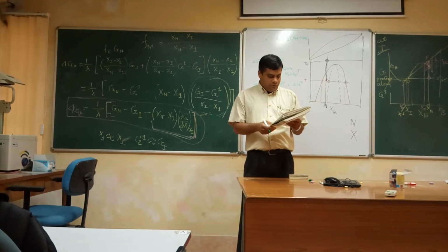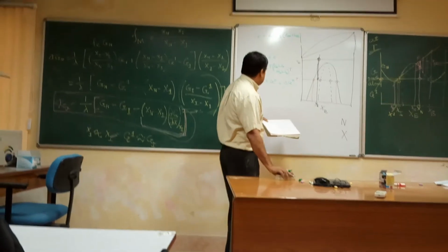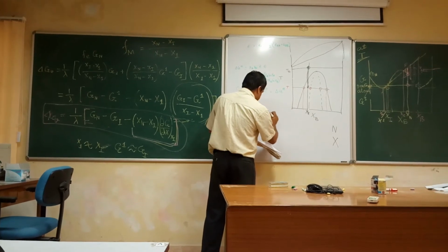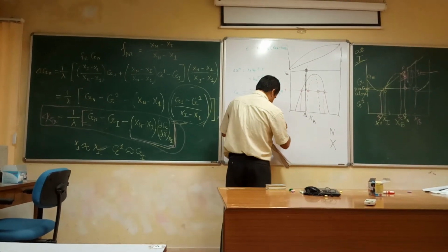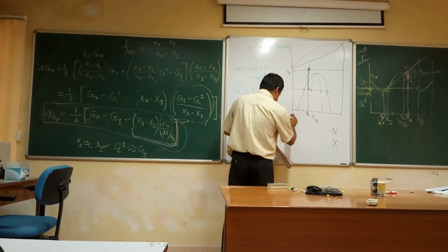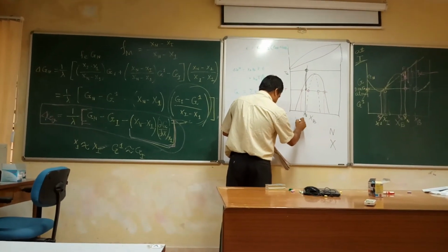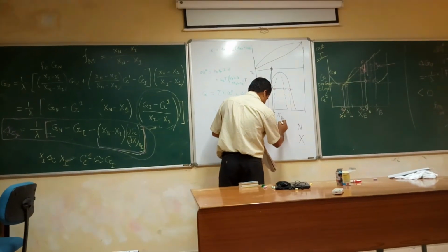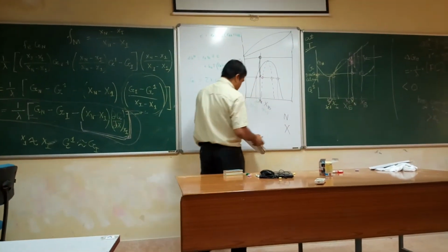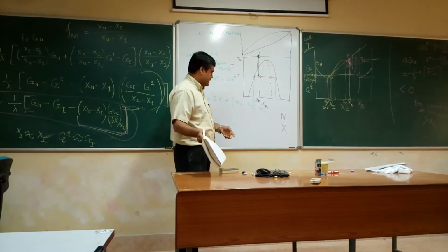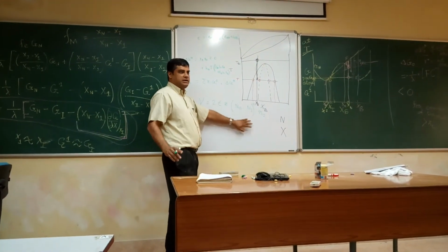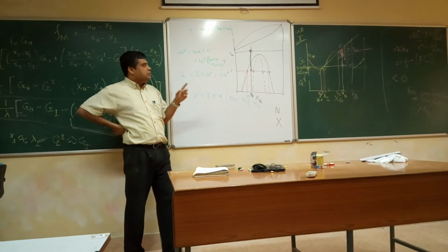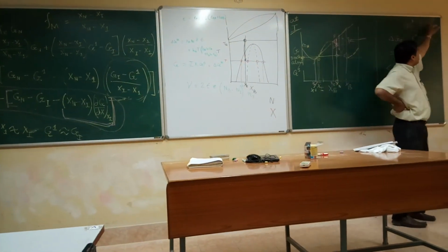And it has been found that gamma is given by 2 epsilon z multiplied by x beta minus xi, whole square, multiplied by the number of atoms situated per unit area of the surface of the nucleus, like Ns star or whatever we did earlier. So you need gamma and delta GV.